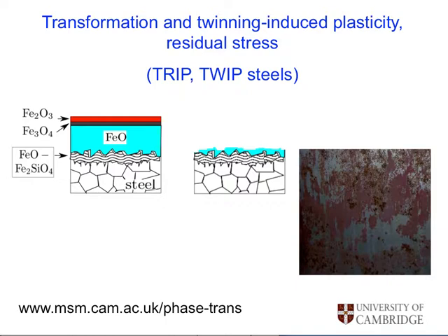So silicon is a problem though, because it forms a low melting temperature oxide during hot rolling deformation called fayalite, the Fe2SiO4, which keys into the material. So it makes the oxide very adherent, and after the cleaning operation where you direct high pressure jets at the steel to remove the oxide, there's still some left which then becomes Fe2O3, which has a red color.